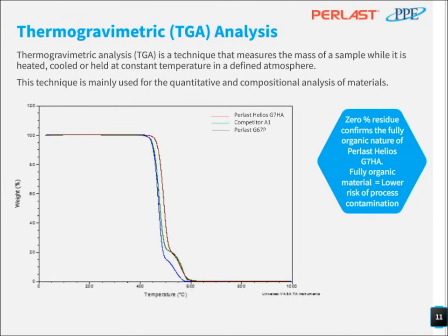is commonly used. Just in case you're not familiar with TGA, I can basically describe it as a very sensitive balance sitting in a furnace. And we put a very small portion of elastomer on the balance pan and increase the temperature in nitrogen environment at a certain rate. At 600 degrees Celsius, we turn on the air to burn off all the organics because of the oxygen, and further increase temperature to 1000 degrees Celsius.